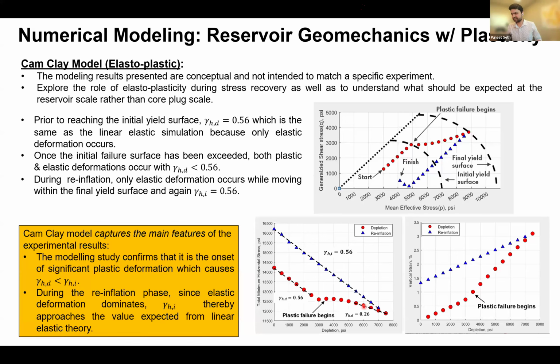And also very interesting, the depletion coefficients. See, when the plastic failure begins, when it reaches that yield surface, the depletion coefficient is much lower than what was observed when elastic deformation was dominating. What happens during re-inflation? We're basically decreasing the effective stresses, and as you would expect, since this is elastic deformation, the injection coefficient is the same as the depletion coefficient when the sample was in the elastic regime. So you get the same value.